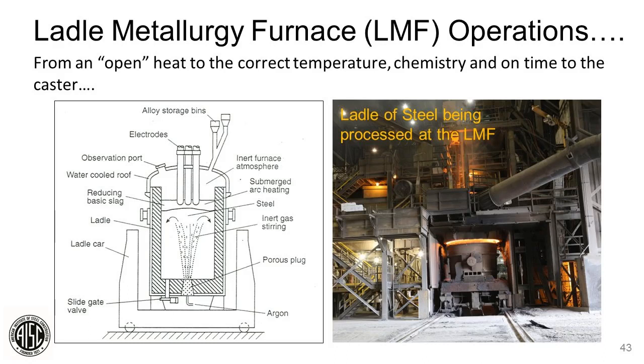We use argon to stir the steel. And then you have a liquid steel layer. Then right above that is the slag layer, which is, again, high cal lime with some flux additions added, and you have the electrode arms coming through the roof. They're arcing on the top, and the roof is water cooled, and it's all sitting on a trolley car so we can slide it in and out. If you look at the picture on the right, you can see the rails so that we can have a ladle on either side of the LMF, bring one in, kick one out, depending on what we need as far as moving ladles and steel around the furnace and the melt shop, rather. So next slide.